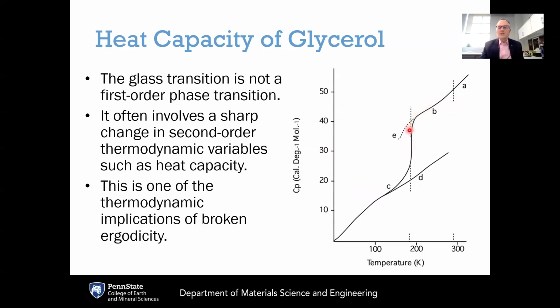You see that there is a loss of ergodicity, which involves a freezing in of the configurations of the liquid into the glassy state. And when those configurations become frozen, there's a loss of the configurational contributions to the thermodynamic properties, and therefore a rather sharp drop in heat capacity, because at low temperatures here, the only contribution to the heat capacity is due to vibrations, since different configurations are not accessible. So this loss of heat capacity corresponds to the loss of the configurational part of the heat capacity. And this is the regime where ergodicity is broken as the system undergoes the glass transition.